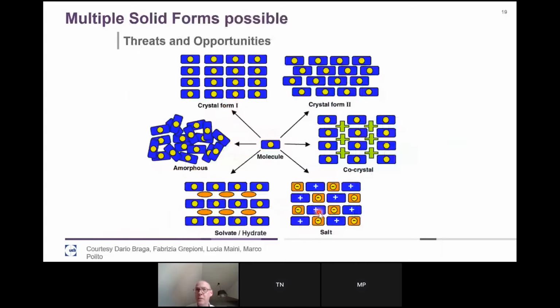To make it more complicated, and now I'm approaching the end of my story, you can not only have crystal forms of the pure molecule, different polymorphs, you can also have, with other components, other molecules, other crystal forms. An API, mixed with excipients for instance, can create a new crystal lattice which incorporates another molecule, which is called a co-crystal. It can do this also with solvent, then you call it a solvate, or with water, then you call it a hydrate. But then the water really has a specific position in the crystal lattice. It's not just thrown between the molecules. If you have charge transfer, for instance an acid that protonates the API, then you speak about a salt.